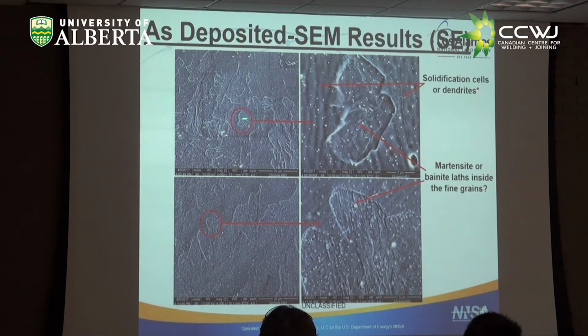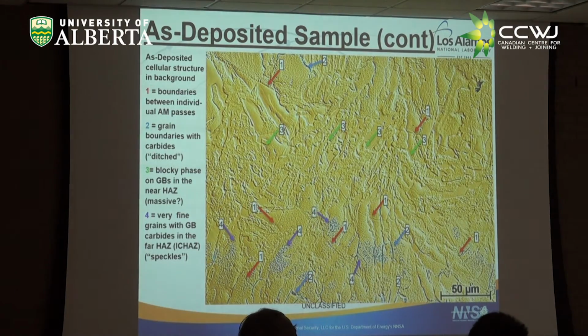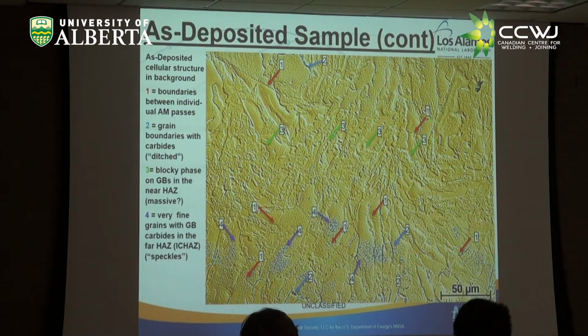Looking at this little region here at higher mag, you can see, ladies and gentlemen, the solidification structure in the background there, right? You can still see it here as well, the cellular structure we spoke about. Irrefutable evidence of solidification. Now, why is this weird in steel? Can anyone tell me? In pretty much every steel, there's a solid state transformation that'll erase this solidification microstructure, and you never see that at room temperature. Yet we still see that right now. That's an important clue later.